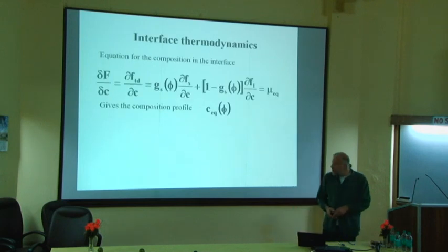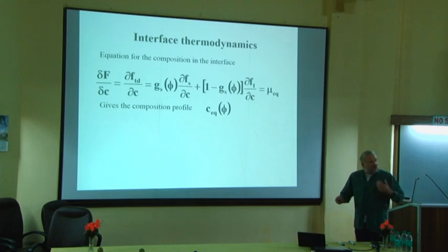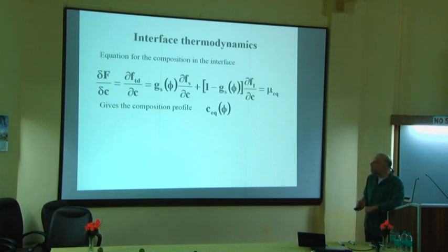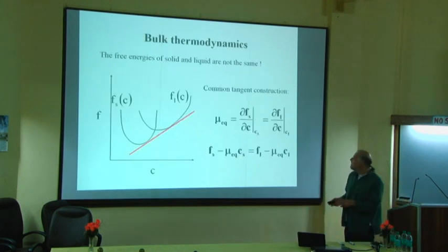So to state this in a little bit more precise manner and to picture what should be a way out, let's look a little bit at this equilibrium interface solution. As I have said, the common tangent construction that gives you the phase diagram fixes the slope of this red line.